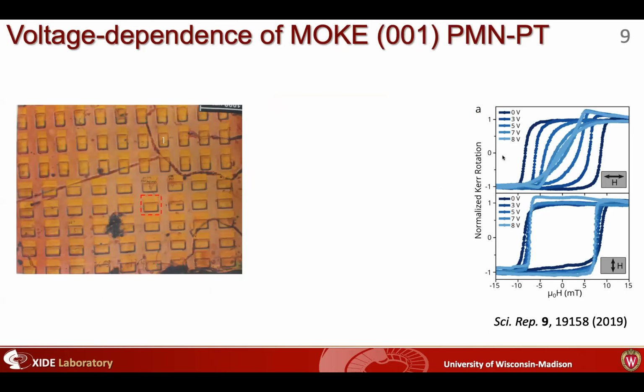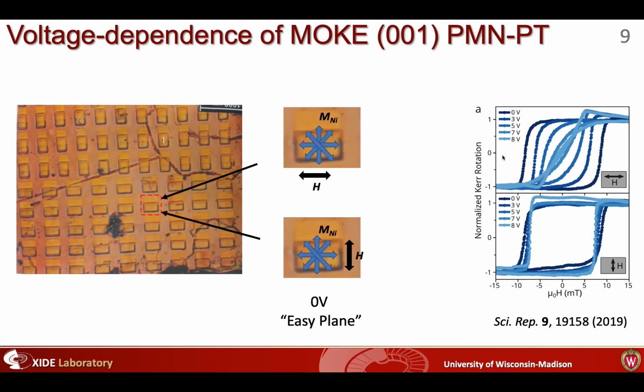So to begin, it's kind of tricky because I like to plot a lot of these MOKE loops all at the same time. And again, we're kind of sensitive to which direction that we're applying the magnetic field. So if you focus on the darkest blue curve, that's our 0 volt state. And if we have the magnetic field at 0 degrees or 90 degrees, it looks more or less unchanged. And if we rotated the other degrees between 0 and 90, we find that we have kind of this easy plane as grown anisotropy in our nickel films.